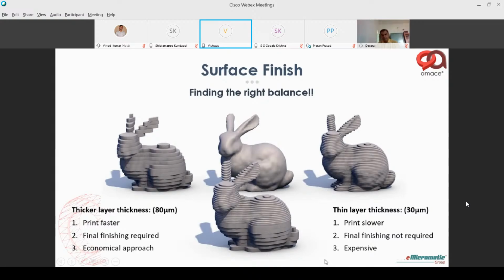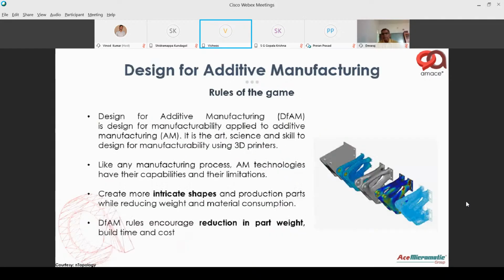But you also have the option of printing in a hybrid, what you see in the middle here, where you have coarser areas which don't need too much finesse. You could go ahead and print those in larger thickness, and then when you have finer aspects, you can print in lower thickness. Eventually you'd want a surface finish as shown in the image at the back, a smoother surface finish, which is achievable through post-processing. So it's all about finding the right balance.